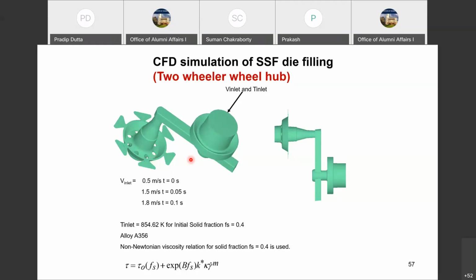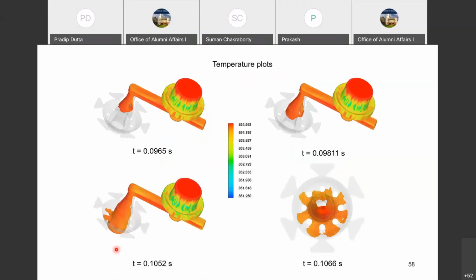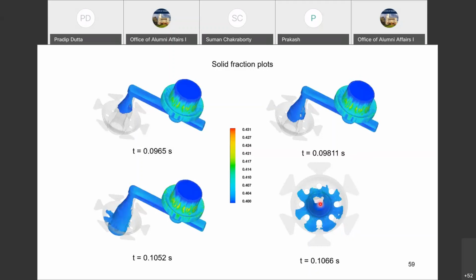And then of course for the viscosity, again we did experiments with our viscometer on the semi-solid material at that elevated temperature, and then we did a curve fitting to come up with a rheological model. And then we ran our CFD model. We used Flow 3D software for this. This is of course the temperature plot, progressively as the die is filling, and this is at an intermediate state. The die gets filled finally, and this is the same at the same time frames.